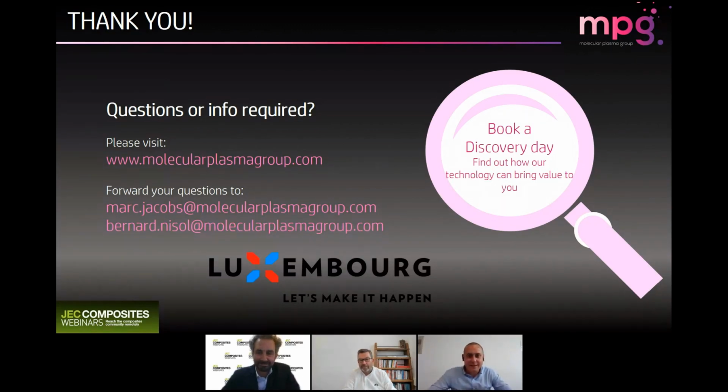So that will strongly depend on the precursor you're depositing, but I must stress at the very beginning that the pinholes will not come from the plasma itself, like what happens in some DBDs. I've been working for years on that topic, and indeed, in some cases, you end up with pinhole-containing coatings, and the damage is done by streamers in the discharge. Here we have APGDs, so glow discharge or Townsend discharges that are streamer-free, and by the way, we're working in the afterglow, so there are no such things as streamers in the discharge. So the plasma will not result in the presence of pinholes.